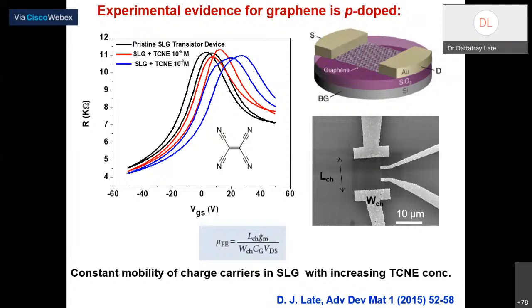So what we have done here, we measured the properties of the device in pristine form. For example, this black color is the pristine device, and we started adding different concentrations of TCNE. For example, you can see we added TCNE 10 raised to minus 6 molar. You see, we find that there is a slight change in the Dirac point. Earlier the Dirac point was exactly at 0 gate voltage. When we started adding different concentrations of TCNE, you can see it slightly moved towards the positive gate voltage. We added more concentration, for example, TCNE of 10 raised to minus 2 molar. It changed slightly more, towards 20 volts. So the change of the Dirac point towards the positive gate voltage indicates that graphene becomes more p-type in nature.